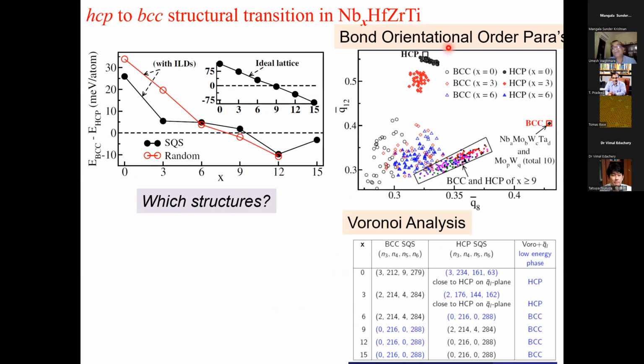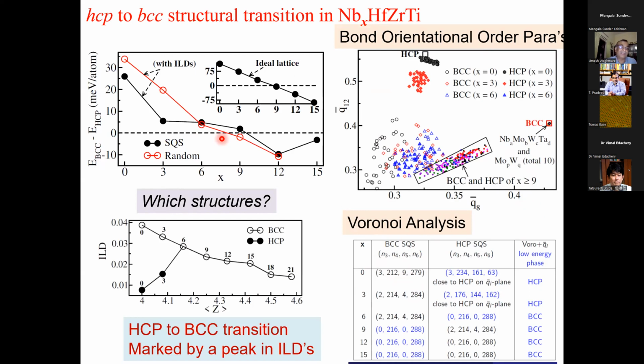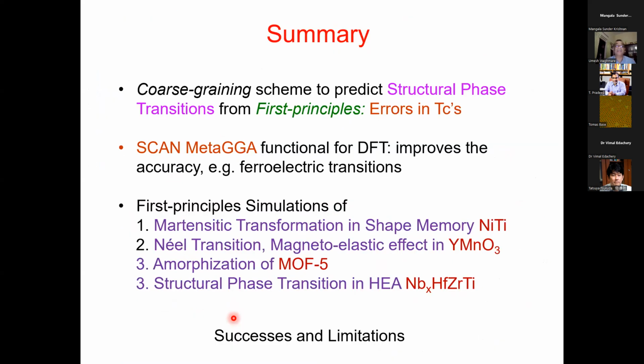So there we use the concept of bond orientational order parameters, which are used in glassy systems, and also Voronoi analysis, which is used in studies of amorphous systems. And from this we infer the crystalline lattice governing that. And very interestingly, we find that internal lattice distortions peak at this phase transition composition. And that's linked with the average number of valence electrons.